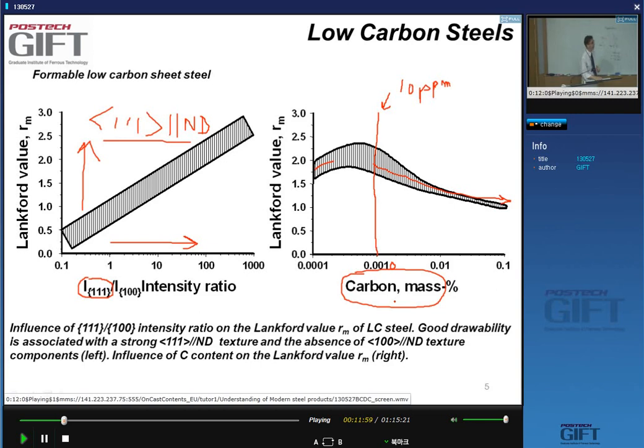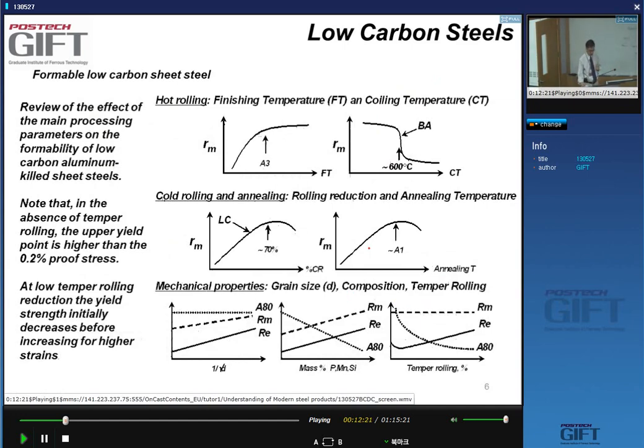What is the carbon content typically of an IF steel? Well, it's about 10 to 20 ppm. Yes, it's extremely low. But low carbon steels will always have a higher carbon content, and an R value and formability lower because of this carbon. However, things are more complex than just removing the yield point and getting a high R value.